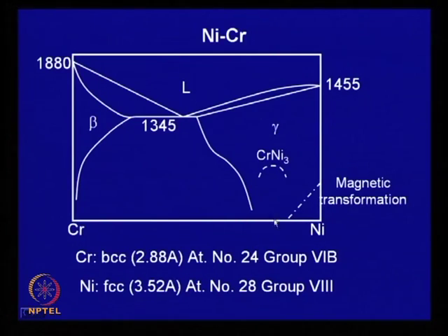In fact, this is the basis alloy on which the superalloys used as gas turbine alloys have been developed. When the gas turbine engine came up around the time of the Second World War, the best material available was austenitic stainless steel, and later they found that if you add a little amount of aluminium to these heating element alloys, then the high temperature strength increases significantly.